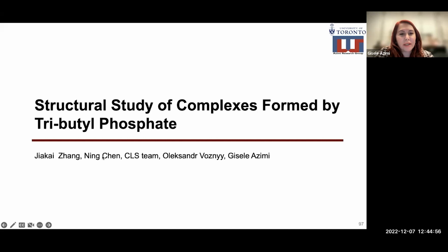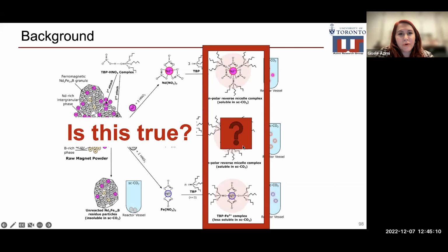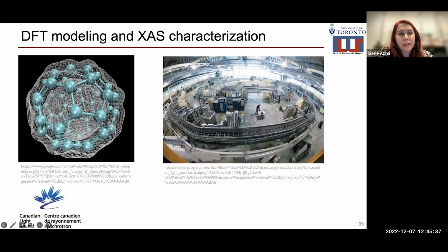We also collaborated with Dr. Ning Chen from Canadian Light Source in Saskatoon, and Professor Voznyy, University of Toronto Scarborough, for DFT calculations. As I showed you before, we proposed this mechanism in one of our projects. For example, for neodymium, we consider neodymium that is chelating with 3 nitrate and 3 TBP. And iron has the same structure for iron 3, and iron 2 was iron 2 with 2 nitrate and 2 TBP. We wanted to prove that this hypothetical structure is true. We performed DFT calculations with Professor Voznyy, and we also performed X-ray absorption spectroscopy characterization in the Canadian Light Source